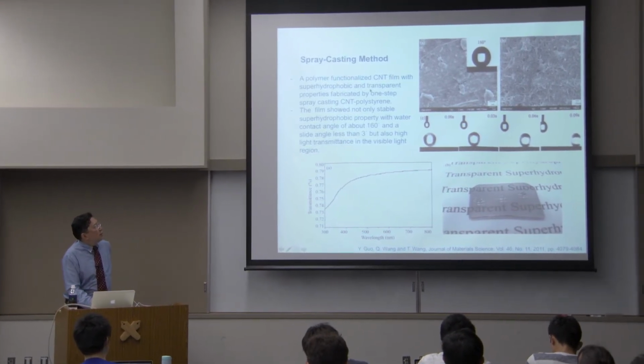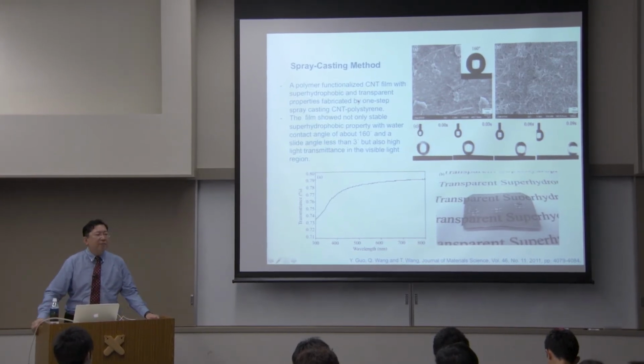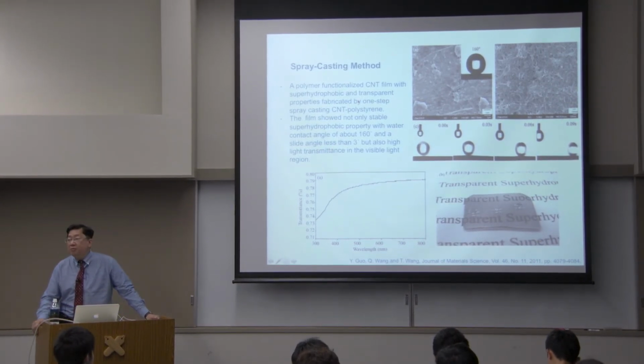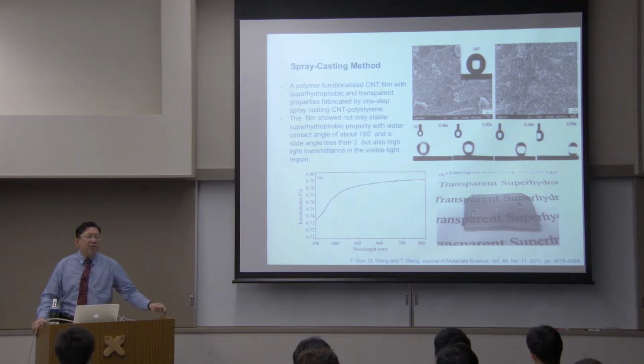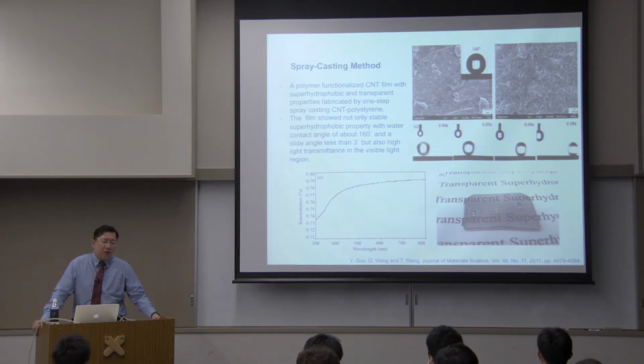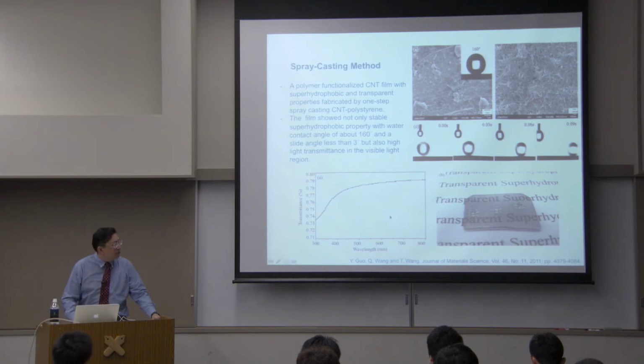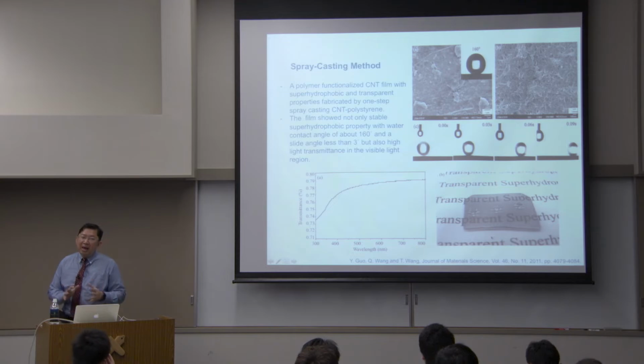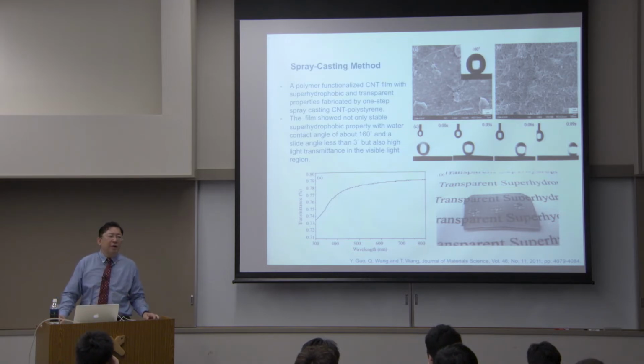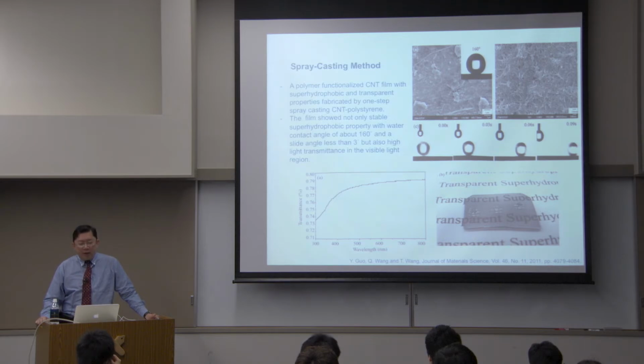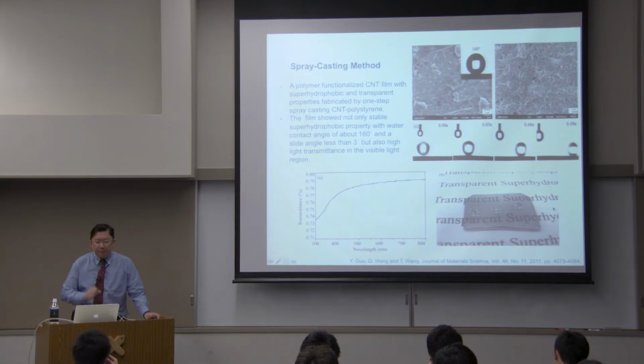The use of carbon nanotube and polystyrene provides a high transmission surface, because a very thin layer of this carbon nanotube and polymer film allows it to maintain its transmission properties. A carbon nanotube is essentially black or greenish in color, but with a very thin carbon nanotube coating, you can still have a high transmission behavior.